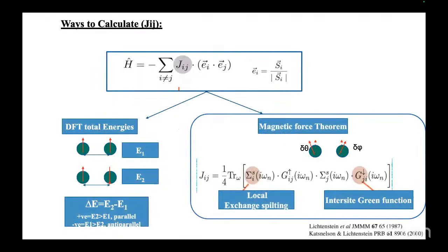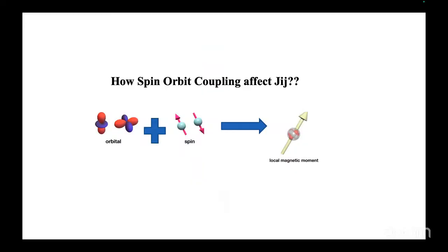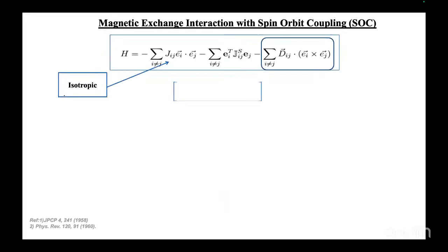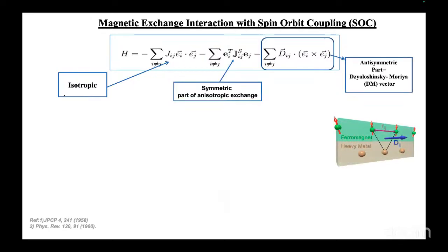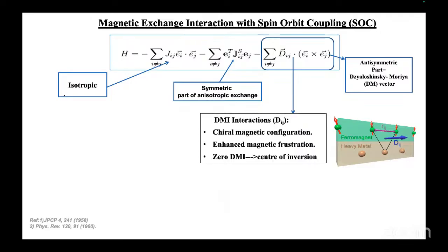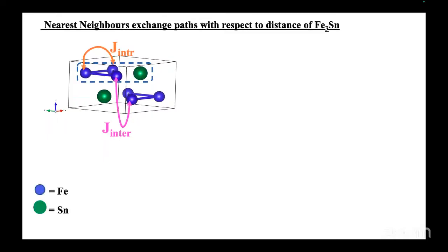This particular expression of Jij in the Hamiltonian modifies when we include spin-orbit coupling, because the spin and the orbital channels combine. It further extends from the isotropic part to include the anisotropic part: the first is the symmetric part of the anisotropic exchange, and then this third term is the antisymmetric part of the anisotropic exchange, that is the Dzyaloshinskii-Moriya interaction, which is very significant to understand whether the system has collinearity or not, because it tells whether the system has some kind of spin frustration or some kind of chirality. One can also get to know if the system has a center of inversion. If it does, then the DMI becomes 0 in the system. So it gives a lot of information. Based on this methodological part, I will now show you which terms I have calculated for the Jij interactions and how I have calculated them.